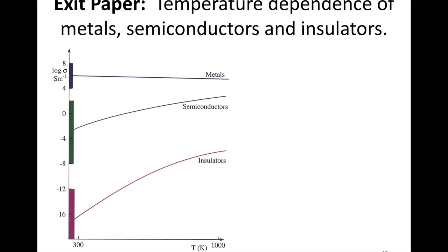There's more thermal energy, and so more electrons go across the band gap and leave behind electron holes at higher temperatures. And so overall, if we factor in both the mobility and the concentration factors, and the charge doesn't change, then we see that the conductivity goes up, and quite drastically.